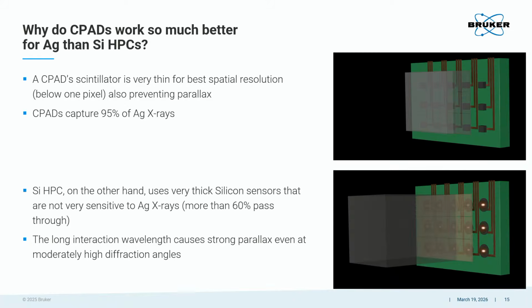Yeah. And really important in this case is the high absorption efficiency for moly and especially silver. And because we use a very thin scintillator, we also don't have any parallax. So here's a good representation. People don't realize how thick, in the lower image, the silicon sensor of an HPC is. It's very thick. Typical sensors are 600 micrometers to a millimeter. Okay, 0.6 to a millimeter. And the scintillators are very thin, like 40 micrometers. Oh, wow. So you get the idea.